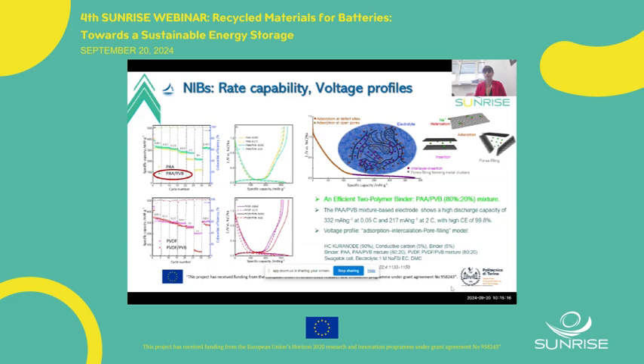First is the poor rate performance and another is poor initial Coulombic efficiency. As we can see, the performance of the laminate that we made, the PAA-PVB mixture 80-20%, the green one, shows the best performance in terms of the rate capability from low C rate to high C rate. It also shows very high initial Coulombic efficiency of around 87%.